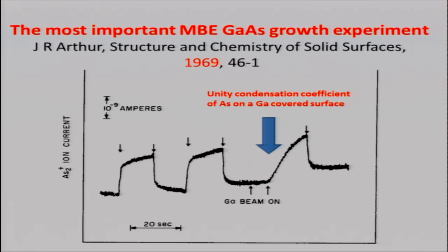The important thing here is that when you get to here, he turned on the gallium beam on the surface. You have a gallium-covered gallium arsenide surface. Now, when you open the shutter, look here. The exponential curve starts from the beginning. There's no abrupt increase there. That means A equals zero, unity sticking coefficient.